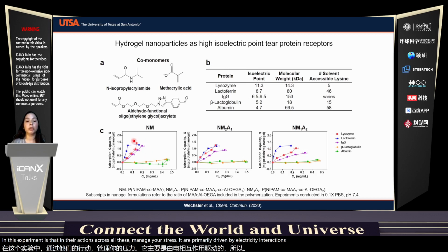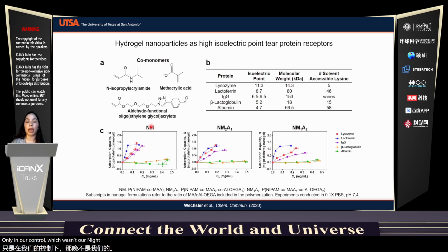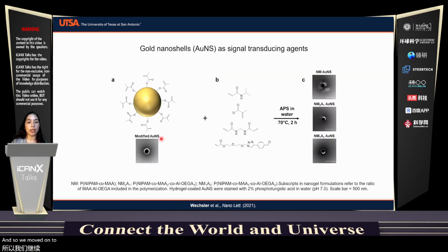So we observed the highest adsorption capacities only in our control, which was our NIPAM-co-methacrylic acid. So even without the addition of our covalent monomer incorporated into our hydrogels. And so this was interesting to us because at the bulk nanogel level, we only observed the effects of electrostatic interaction. So this was quite interesting to us at this point. And so we moved on to investigate the use of our signal transducing agent when we incorporated our gold nanoshells